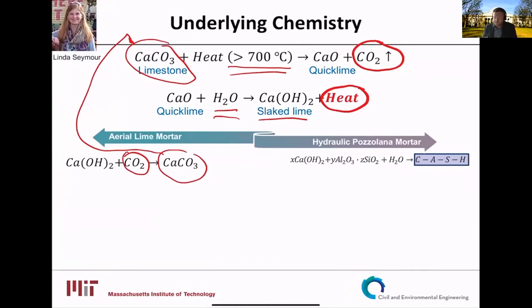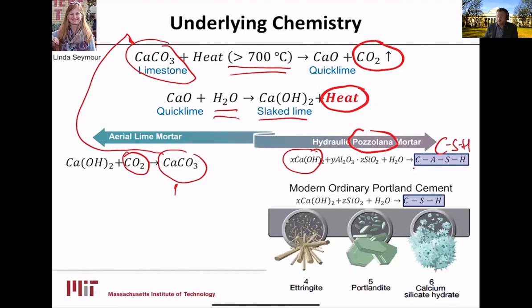But Romans then put these pozzolans into reaction. And pozzolans would take this lime to another product, not the calcium carbonate that would reabsorb, but calcium aluminum silicate hydrates. And you see, I already mentioned calcium silicate hydrates, CSH, which is very similar to what we have seen in ordinary Portland cement. So in this slide, you do see the connection between modern and old through these hydrates that are actually the key for the integrity of our concrete structure.